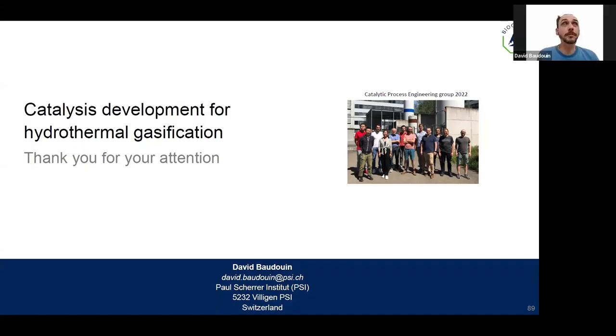So this is typically met at 400 degrees C, at least at the conditions we applied. I can 100% tell you that it's happening at 400 degrees C, and the reaction pathway that I introduced is occurring at this temperature. Now, part of it, the first steps, are also observed without catalyst, with glycerol alone in supercritical water, or in near critical water. So I think at 350, the steps are already occurring.